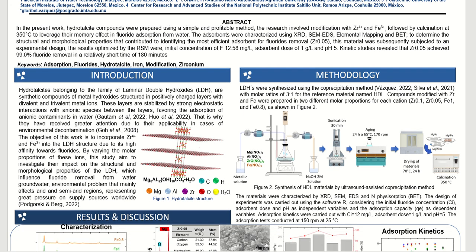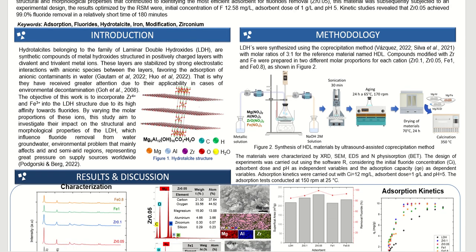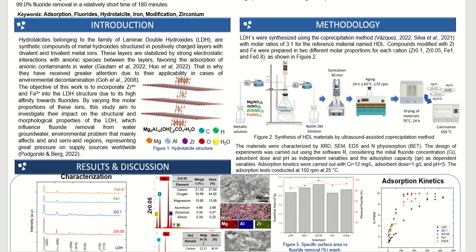These adsorbent materials called hydrotalcite are synthetic compounds of metallic hydroxides, structured in positively charged layers that are stabilized by a strong electrostatic interaction with anionic species between the layers. When calcined, they tend to present a memory effect where hydroxyl groups, water molecules, and carbonates are eliminated, causing a collapse in the structure. However, when placed in contact with anions of interest, in this case fluorides, it has the ability to revert itself and adsorbs them on the surface of the materials, thus eliminating them from the aqueous solution.